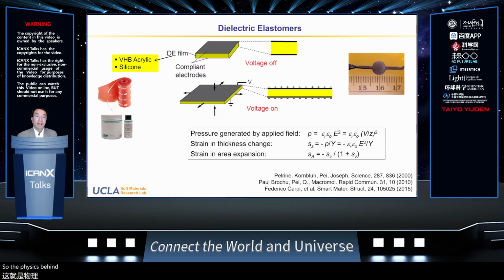So the physics behind this dielectric elastomer is quite simple in a way. The electrostatic pressure, or the Maxwell pressure, is proportional to the dielectric constant of the dielectric elastomer and the square of the electrical field applied across the polymer film. Typically, the polymer films we use are around 30 to 40 microns thick, and the true field applied to the film is on the order of 100 to 400 volts per micron. So we're talking about applying a voltage on the order of a few kilovolts. This is a high voltage applied to this variable capacitor.